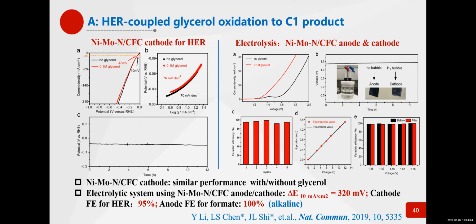electrolyte, you can see that the input voltage can be reduced by about 320 millivolt. And also it shows very high Faraday efficiency. For example, at the cathode for HER, the Faraday efficiency is as high as 95%. And at the anode, in the alkaline media, the Faraday efficiency for formate is about 100%. It is indeed very high.